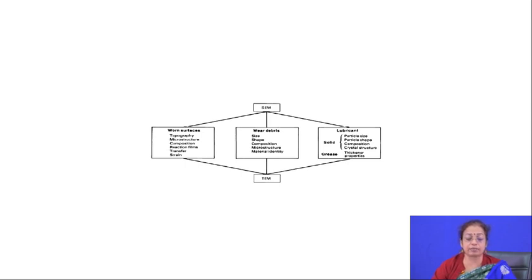So whenever you talk about adhesive wear, you will find that the initial mechanism of wear, or initiation of the wear, is because of adhesive joint formation, but propagation occurs because of three body wear actually. So this three body wear can be abrasive wear, can be adhesive wear, can be anything. For example, if at the interface there would be copper formation, then naturally because of three body wear, the wear rate would be reduced to a little extent, because the presence of copper would act as a lubricant. So after the three body wear, you will find that there will be loss of contact between the two surfaces.